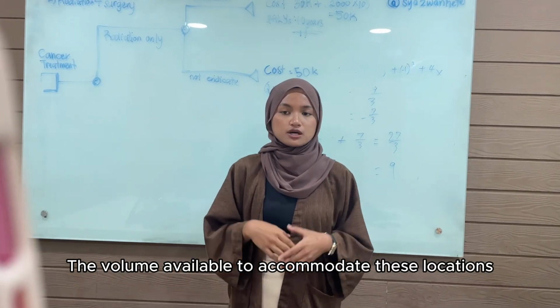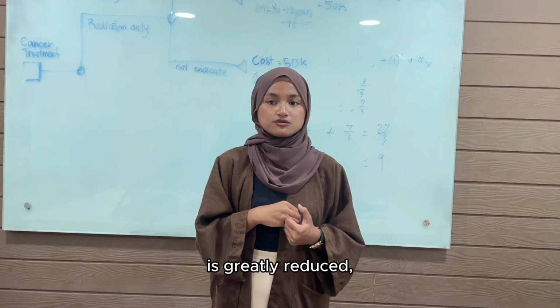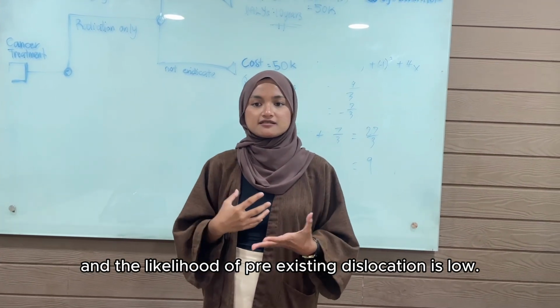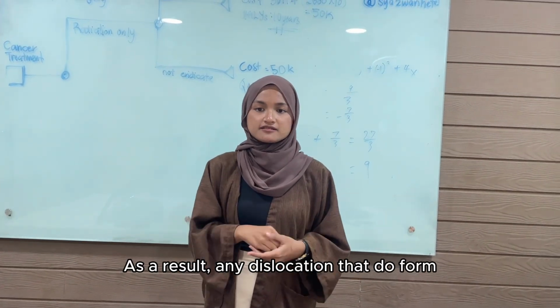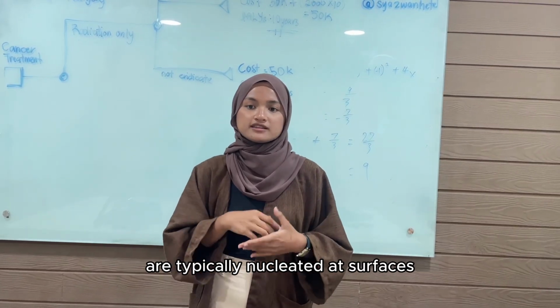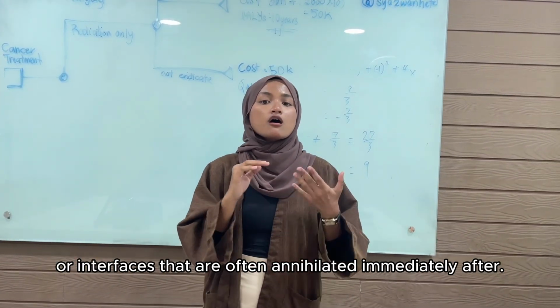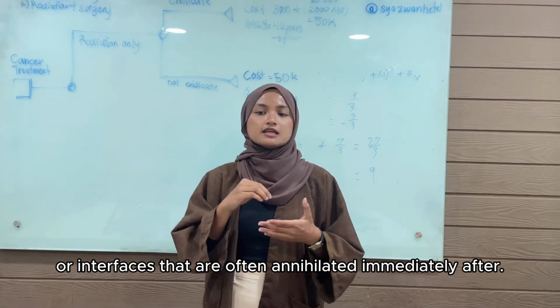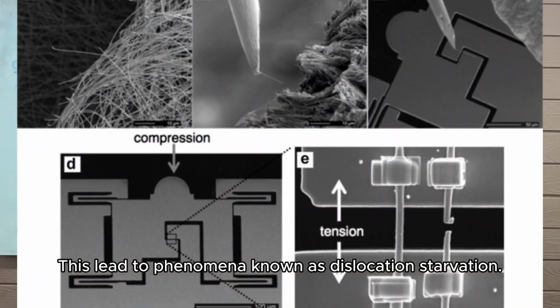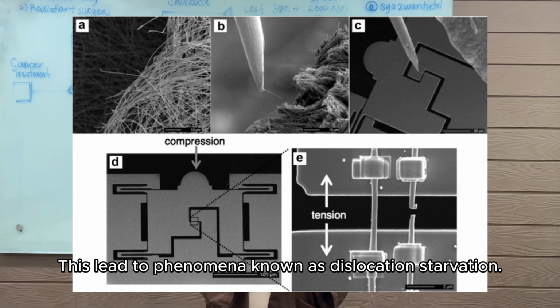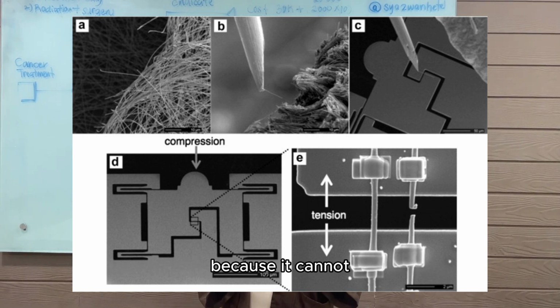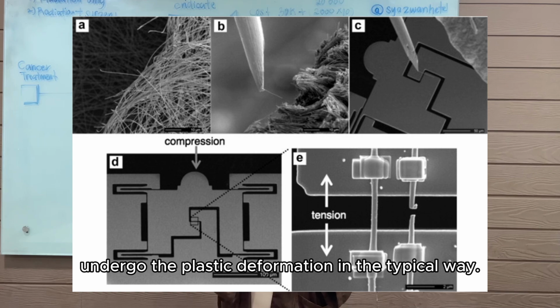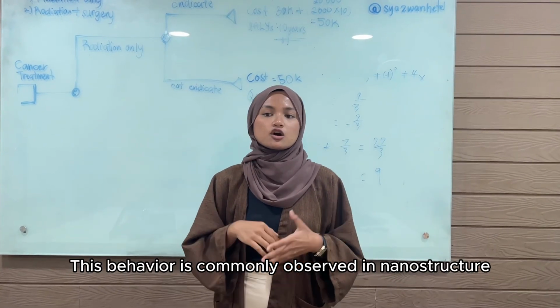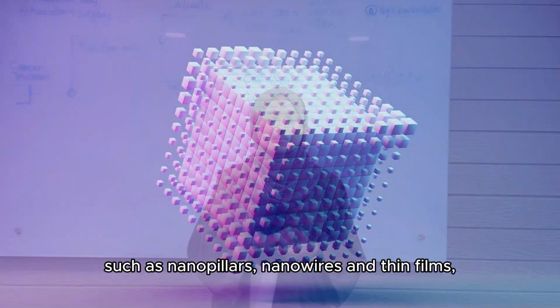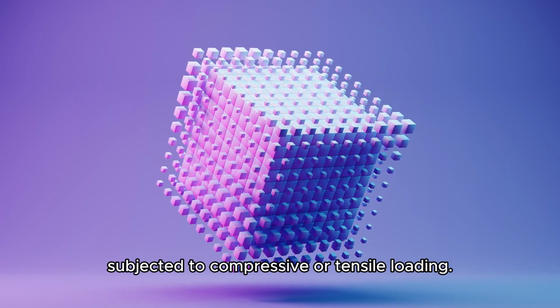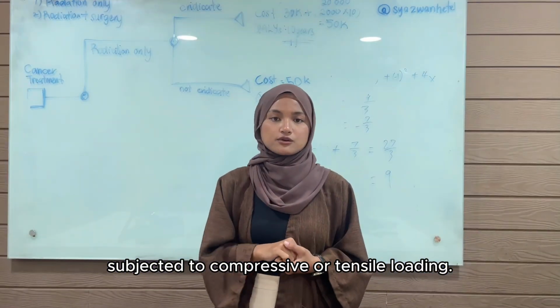The volume available to accommodate dislocations is greatly reduced, and the likelihood of pre-existing dislocations is low. As a result, any dislocations that do form are typically nucleated at surfaces or interfaces and are often annihilated immediately after. This leads to a phenomenon known as dislocation starvation, where the material becomes stronger because it cannot undergo plastic deformation in the typical way. This behavior is commonly observed in nanostructures such as nanopillars, nanowires, and thin films subjected to compressive or tensile loading.